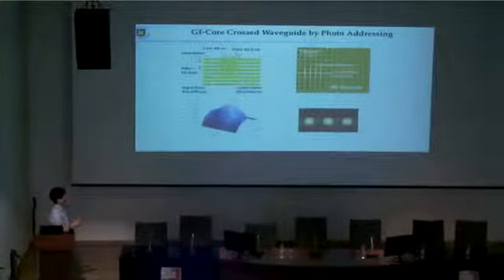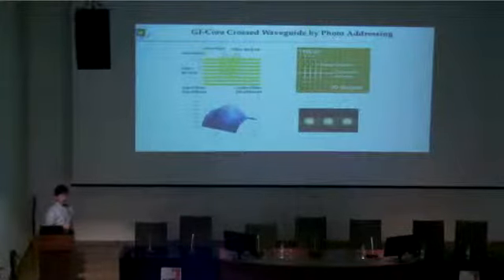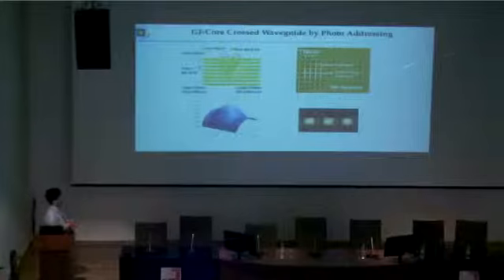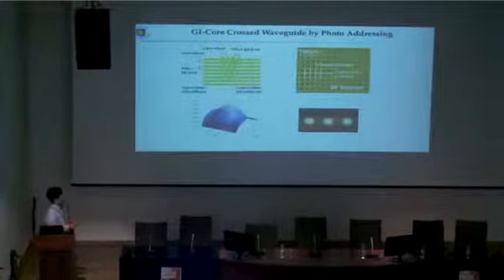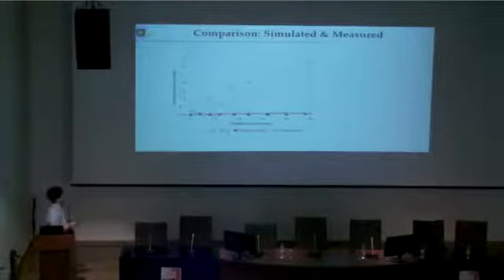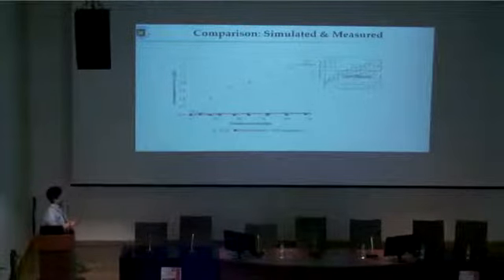By applying this photo addressing method, this kind of perpendicularly crossed waveguiding structure is successfully fabricated. And not only perpendicular, but also other crossing angles are available. Again, a graded index profile is formed in the straight sections, not at the intersection. Here, again, this is the number of crossings, and these plots are measured values. Unfortunately, the photo addressing method cannot make the step in the SI structure, so this measured value is coming from the literature, 0.12 dB per crossing. So the simulated result is slightly lower than this measured value, while good agreement is observed between these graded index square core crossing waveguides.